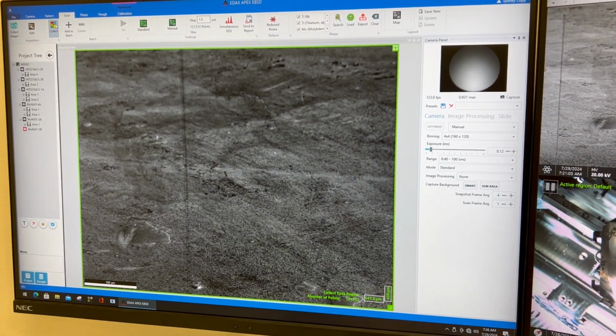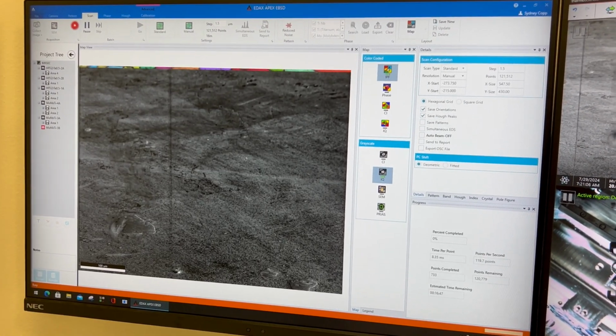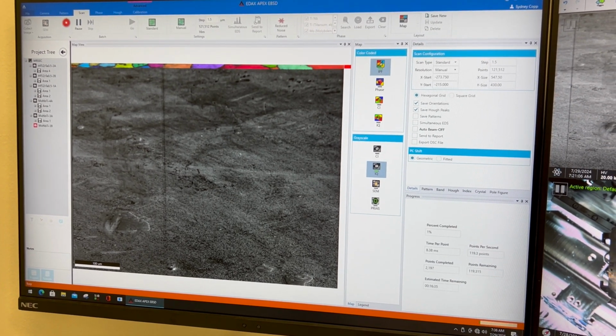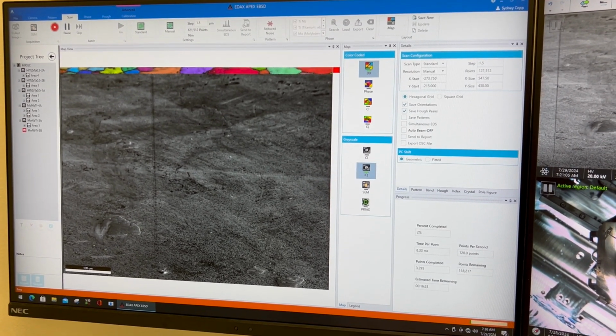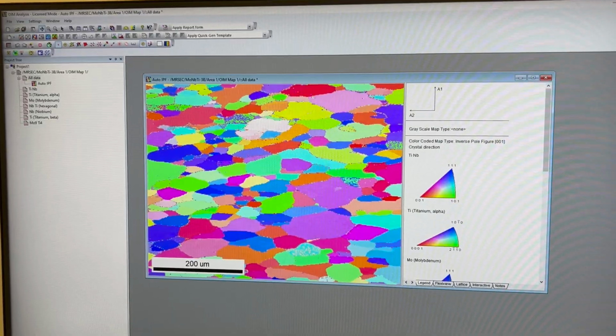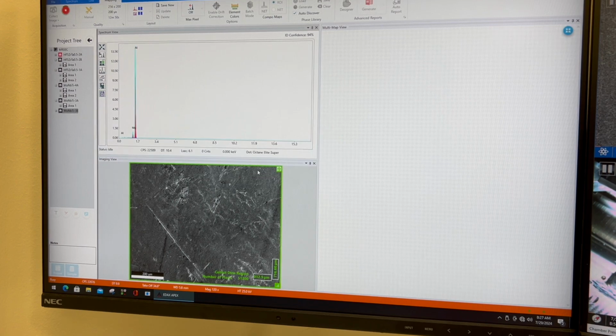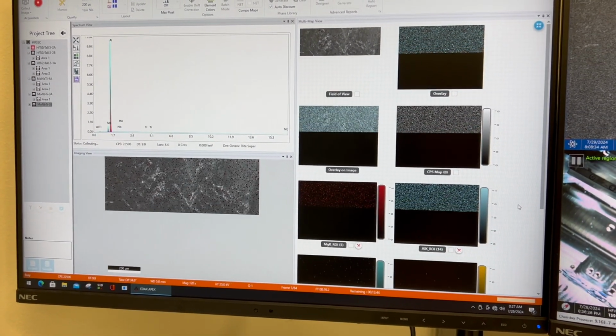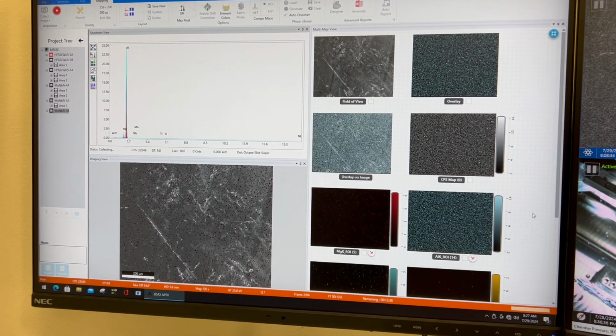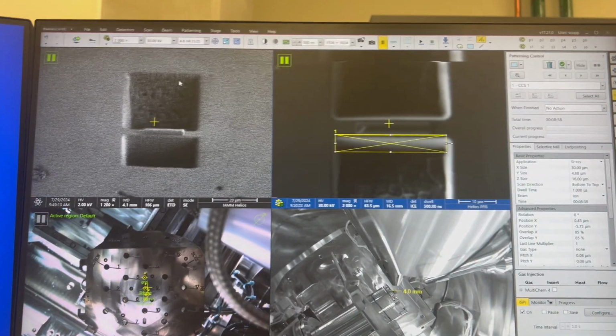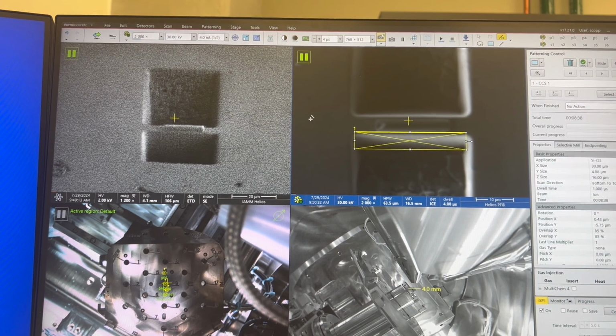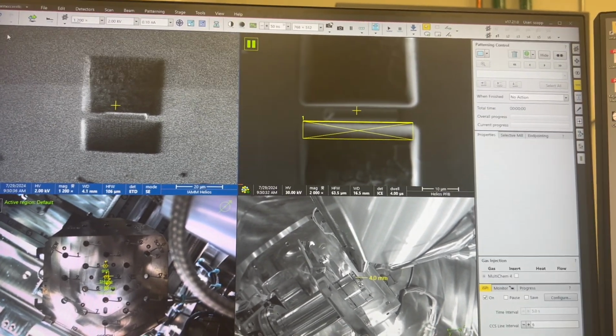Other microscopy characterization techniques include electron backscattering diffraction, also known as EBSD. This allows you to see the crystallographic orientation of grains within the sample. We can also do energy dispersive spectroscopy, or EDS. This technique is best used for chemical characterization of the sample, and it provides both an X-ray spectrum and an elemental map.